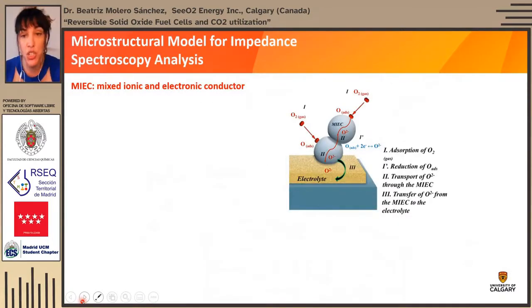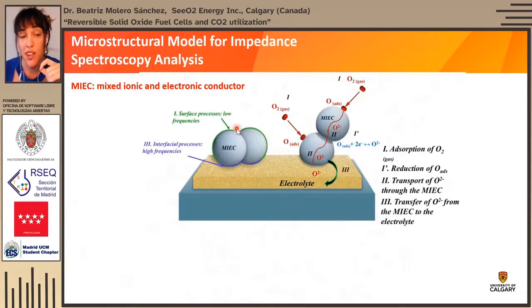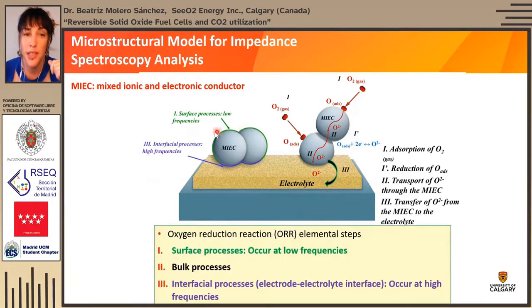So in a nutshell, I won't get much into this, but we use these fittings and these results to try and understand the reactions at the mechanism level. Here is a simple breakdown of what happens in the reduction reaction. We use these results to understand what happens, which is the rate determining step, and what happens at which step. As an example, at low frequencies, we know these are surface processes, so the surface of the catalyst, that would be the solid-gas interface. And at high frequencies, these are interfacial processes or solid interfaces. So it's quite a powerful technique to understand these reactions.